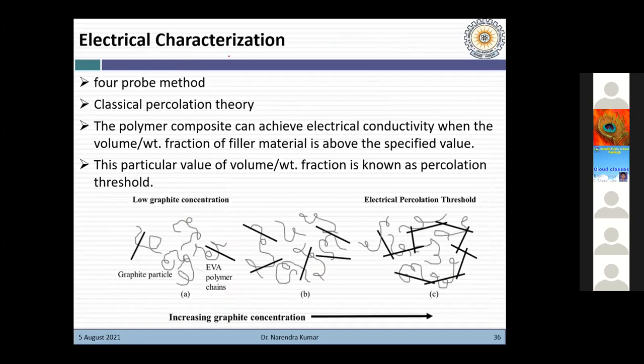So for electrical characterization, we used the 4-probe method, and as per the classical percolation theory, the polymer composite can achieve electrical conductivity when the volume or weight fraction of the filler material is above the specified value. For a lower volume fraction, this is the situation: graphite particles are not touching each other, so that's why this polymer matrix is not electrically conductive. But once we keep on adding the reinforced particles into the polymer matrix, then this is the situation.